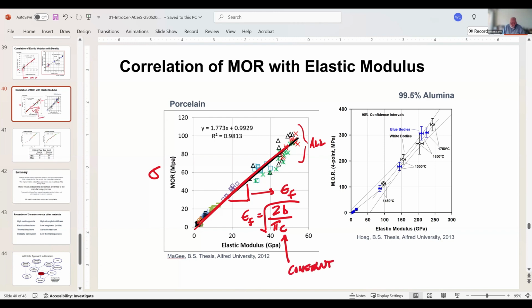So my flaw size, c, is constant because b is constant, 2 is constant, pi is constant. So my failure strain is inversely related to flaw size, and it's a constant. Same here, okay? Failure strain is a function of 1 over c, and it's a constant. What does that mean? That means that my flaws do not change with densification, okay?